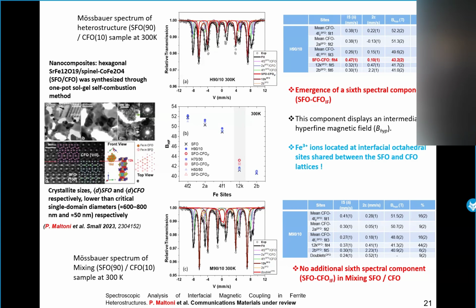Now, in order to confirm this hypothesis, we performed a measurement on a physical mixture of strontium hexaferrite and cobalt ferrite. Normally, in this case, we don't have an interface, and the Mössbauer spectrum at room temperature shows a classical Mössbauer spectrum for strontium hexaferrite. And here the site corresponding to the 12K is characterized by a very narrow line. So using just one subspectrum, it's possible to reproduce it.